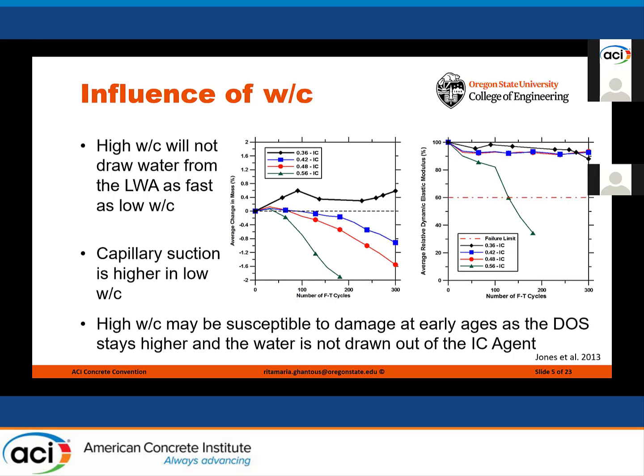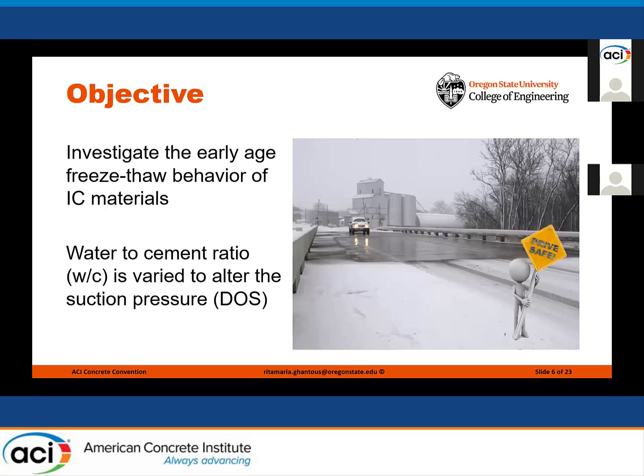So all these results were collected at later age and prove that internal curing for cementitious material with a low water to cement ratio is good, and then the material will resist freeze-thaw environment. But the question we have is what will happen at early ages, and that's the objective of this study, where we are going to investigate the early age freeze-thaw behavior of internally cured cement-based samples with different water to cement ratios.